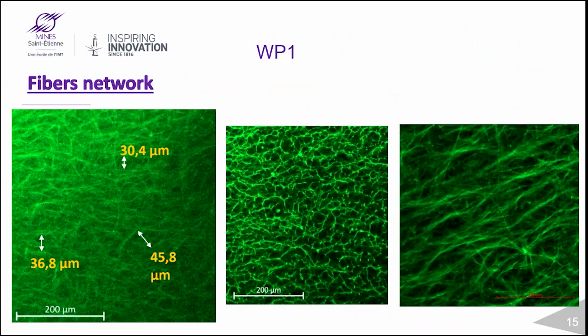The thing is, we observed that we had a limit effect at the bottom where the gel was attached, but also that despite the fact that within the hydrogel we had isotropy, at the surface we observed an alignment of fibers in some cases. So this is probably due to the manipulation of the hydrogel, where the medium just moves the surface fibers and aligns them during manipulation.